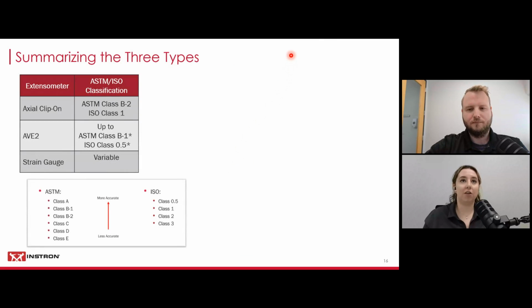So to summarize the 3 types that we just covered in a broad sense, for our axial clip-on, the AVE2, and our bonded strain gauges, in terms of ASTM ISO classification, our clip-on is guaranteed to meet ASTM Class B2 and ISO Class 1. The AVE2 is up to ASTM Class B1 and ISO Class 0.5. And I just have some asterisks because that classification is going to be dependent on the lens that you're testing, which can affect your field of view and the gauge length that you've marked on your specimen.